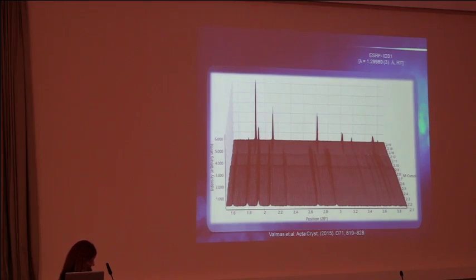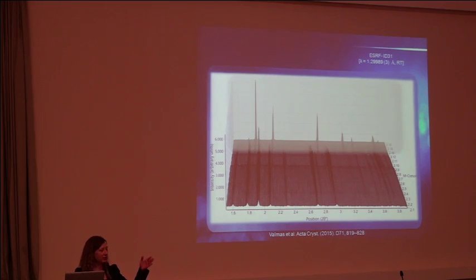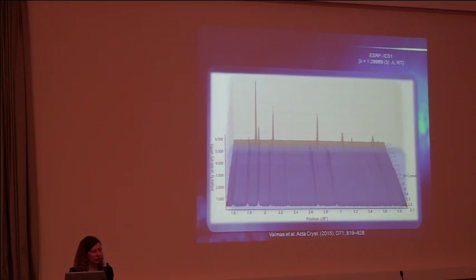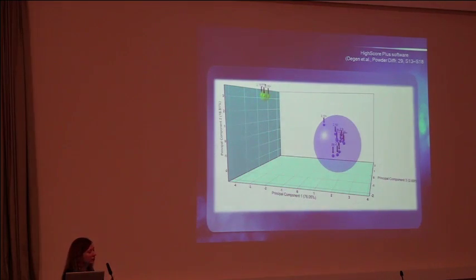We visited the synchrotron, and these are the data of the samples with m-cresol. These are sample codes corresponding to different crystallization pHs. And as shown before, these are all the data collected for a sample series. If you look at them, you see that one set of data has peaks at a certain set of 2 theta angles, and in another set the data dramatically change, and we knew that there is a phase transition. Principal component analysis is a very nice way to very quickly screen your data. It groups, clusters, profiles together based on their similarities, and if we import all of our data in a software, in this case we used HighScore, it separated the profiles into two families, green and blue, based on their similarities, what we could see by eye.